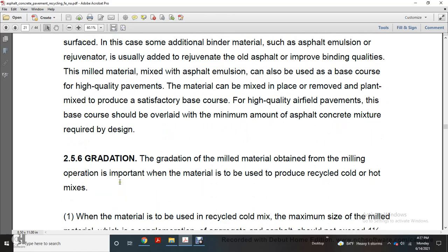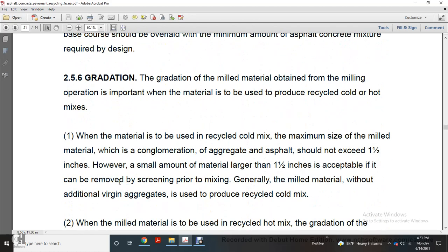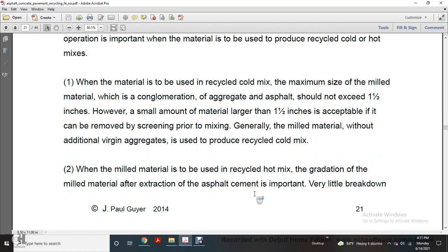The gradation of the milled material obtained with the milling operation is important if the material is to produce recycled cold and hot mixtures. When the material is to be used for recycled cold mix, the size of the milled material, the conglomeration of aggregate and asphalt, should not exceed 1 1/2 inches. However, a small amount of material over 1 1/2 inches is acceptable. That can be removed by screening prior to mixing. Generally, the milled material without additional virgin aggregate is used to produce recycled cold mix.